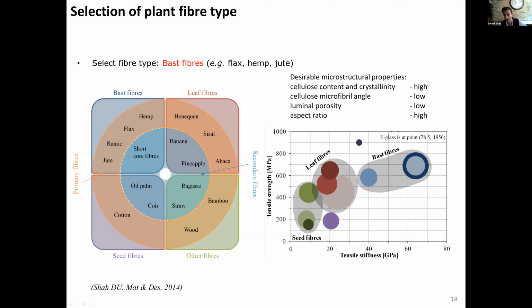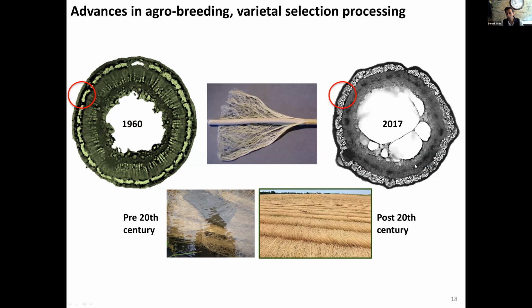But some of the key properties at the microstructure level that give them these high tensile properties are their cellulose content, crystallinity, and the low microfibril angle. Natural fibers can be porous, so you want less porosity, a luminal porosity that is almost non-existent, and high aspect ratios. So we eventually went with flax fibers because it is also one of the industries that is most developed in terms of the textile materials that are available or can be produced from them.